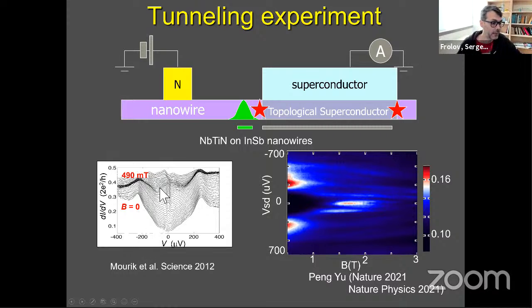So this is our old data, and these both are from the same materials. It's niobium titanium nitride on indium antimonide nanowire. So the older experiments, we are now exploring different superconductors like tin or things like that. But all these data have these features, like, for instance, look at the bottom trace on the left. It has the two peaks at finite voltage bias, about 250 microvolts plus and minus. Those are the manifestations of the induced gap from the superconductor in the semiconductor.